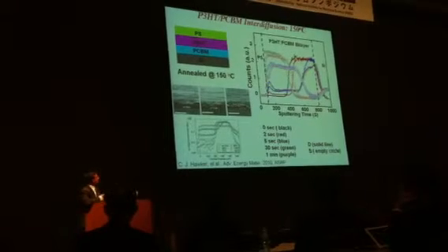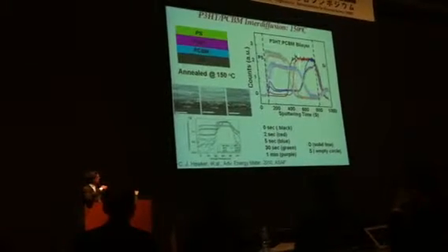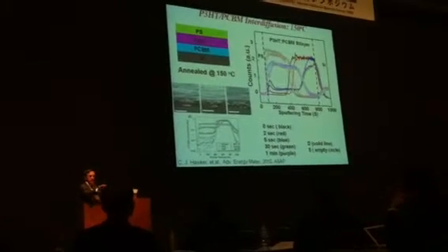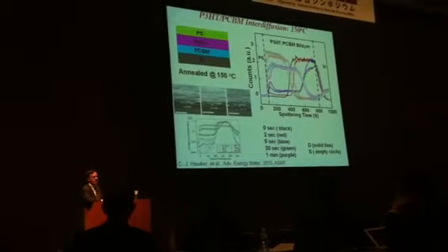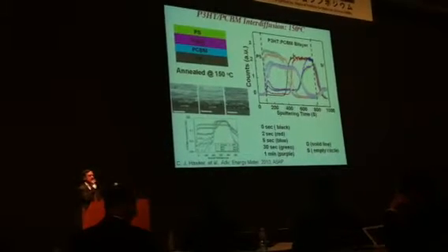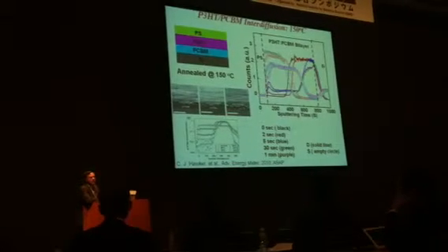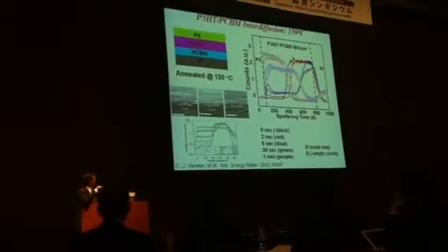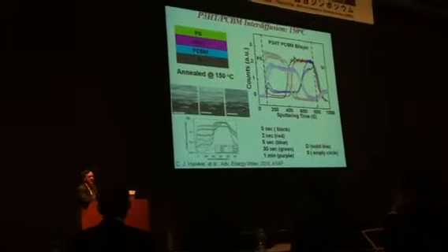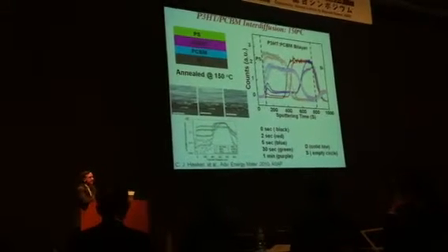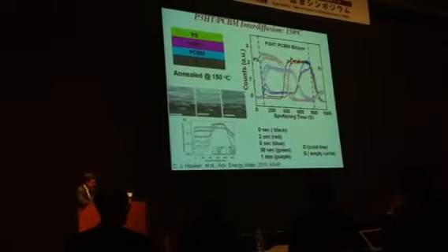If we heat it a little bit further, we find that the position of the interface has changed as more PCBM is being drawn into the P3HT, but we maintain this constant profile of PCBM in the P3HT layer. We do see a development of an excess at the surface, and in fact the PCBM penetrates through the P3HT layer and you get crystallization on the surface.